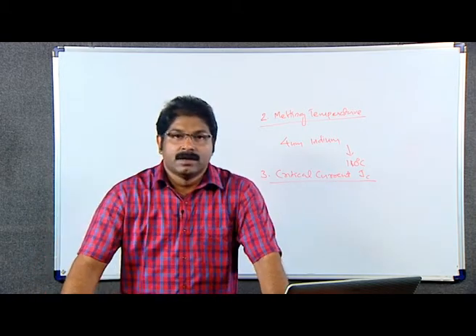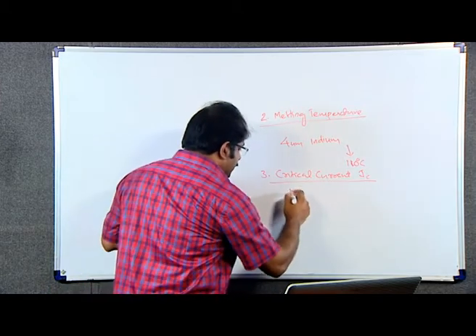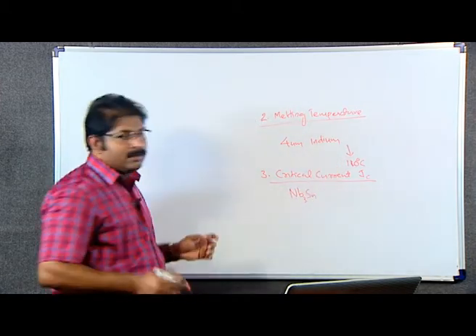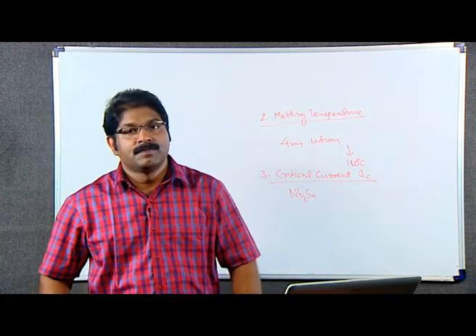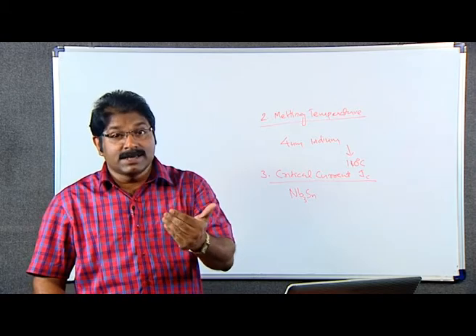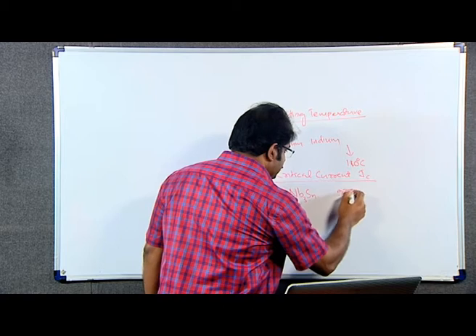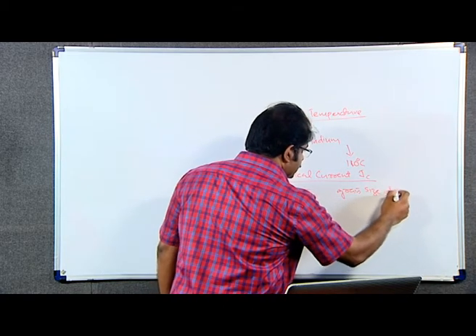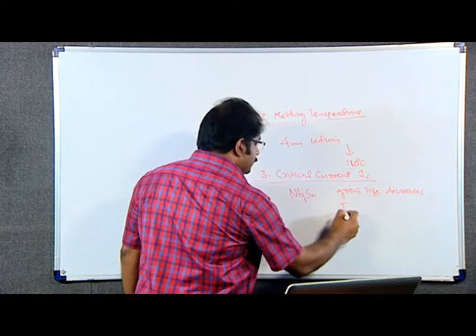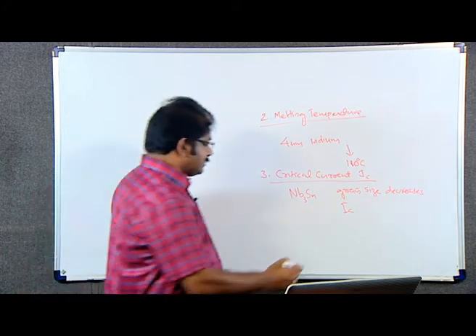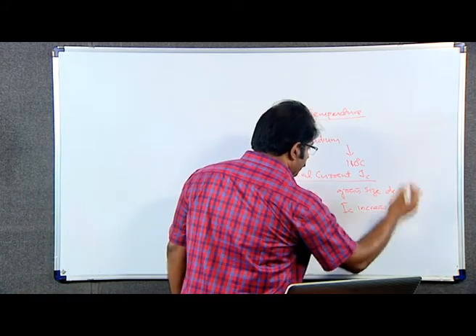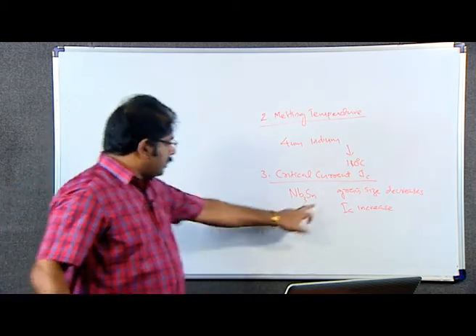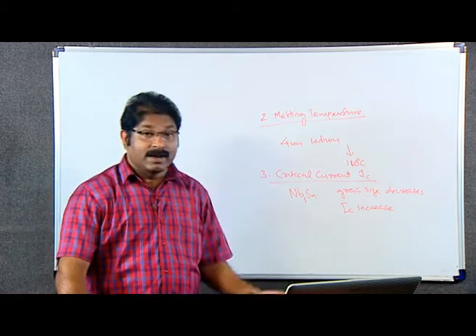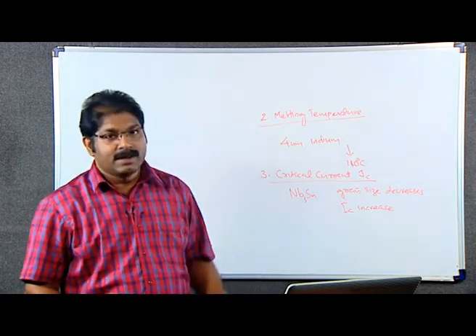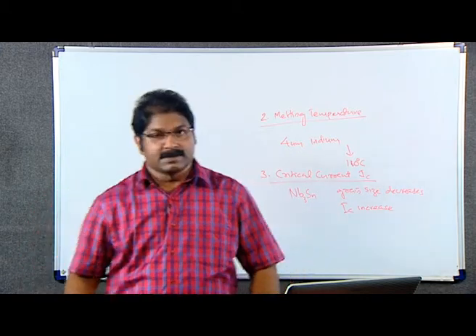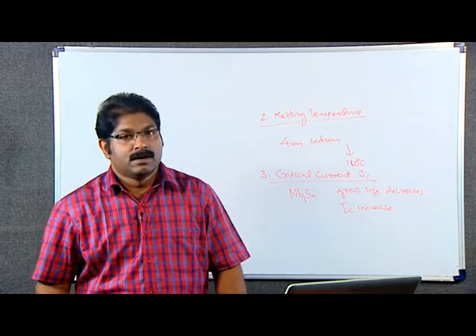Let us see a material. In Nb3Sn, niobium tin, this is a superconductor, it is a bulk nanomaterial. It is found that as the grain size decreases, the critical current is found to increase. So, if you make a material with lower grain size of niobium tin, you can increase its critical current, which means you can give more current to the material and keep the superconducting behavior intact. And this has very big practical applications.